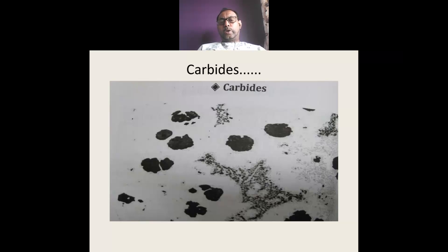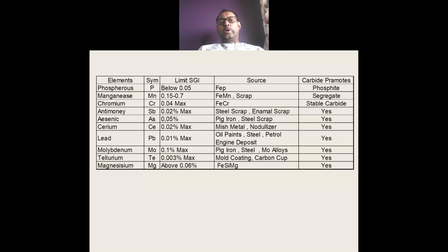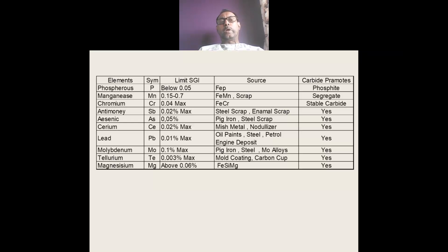In conclusion, these are the elements which, if they go above the limit, can cause carbide promotion. Phosphorus above 0.05% will give you carbide — that is, phosphide eutectic — so controlling phosphorus below 0.05% is very important. Manganese can give you segregation if it is above 0.7% in ductile iron.